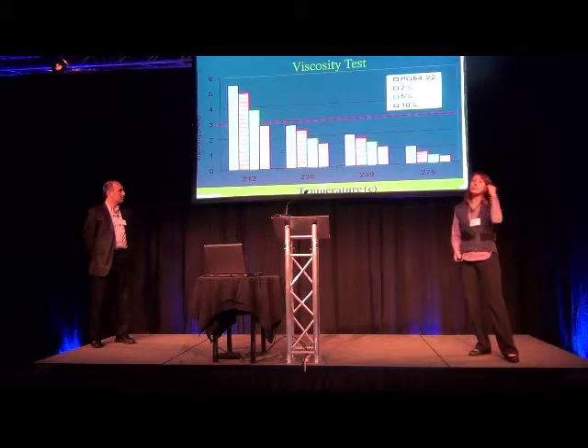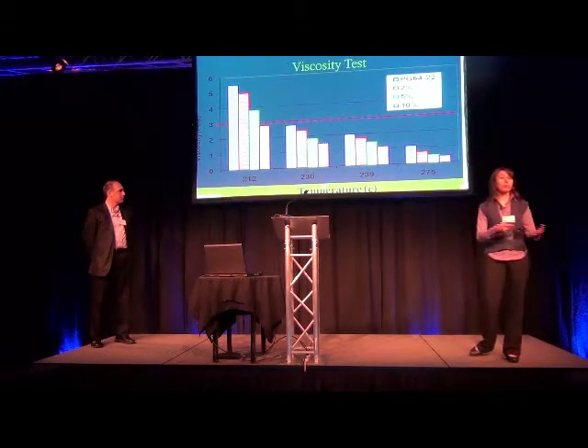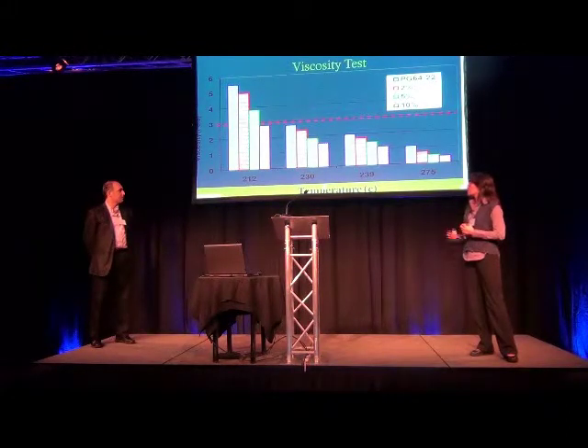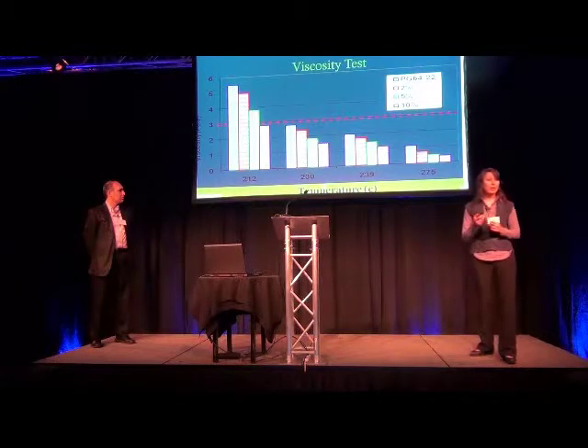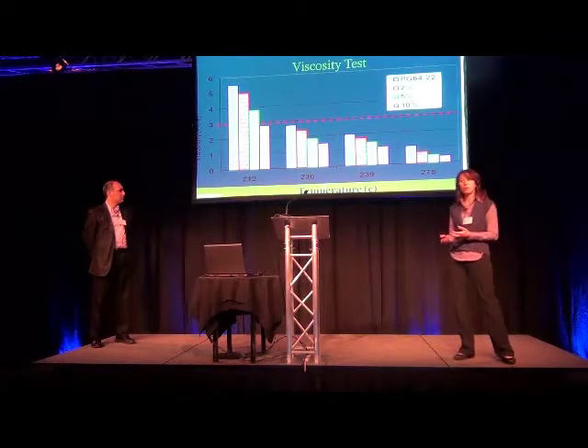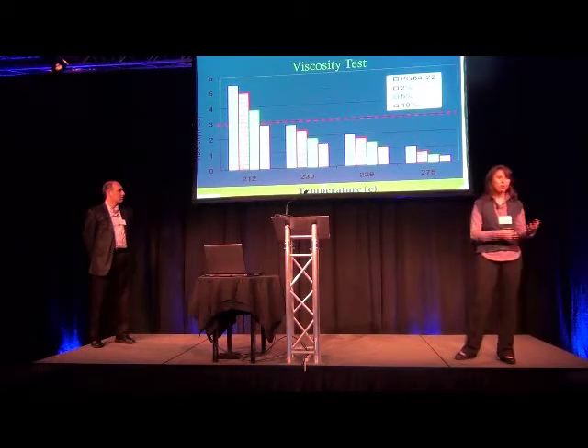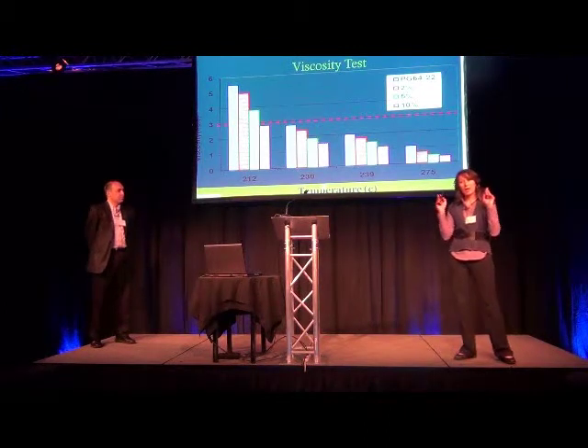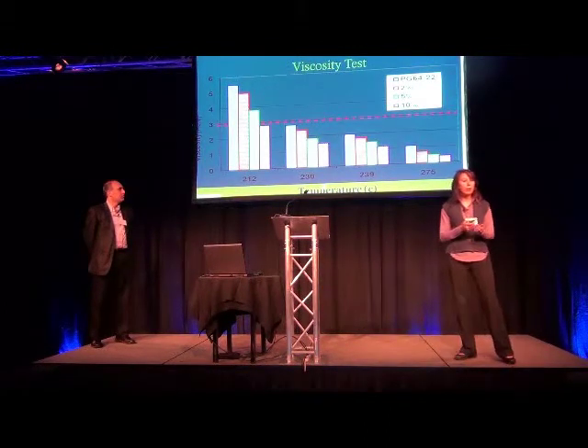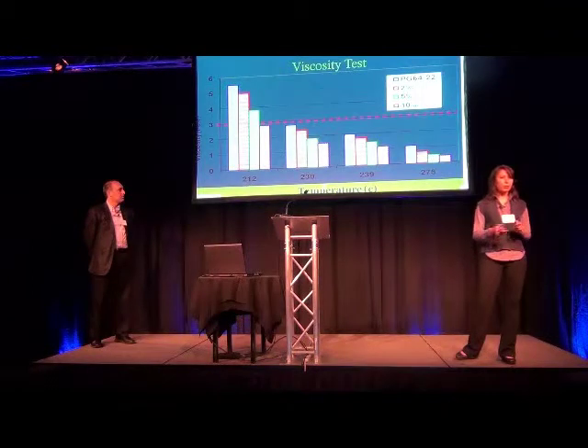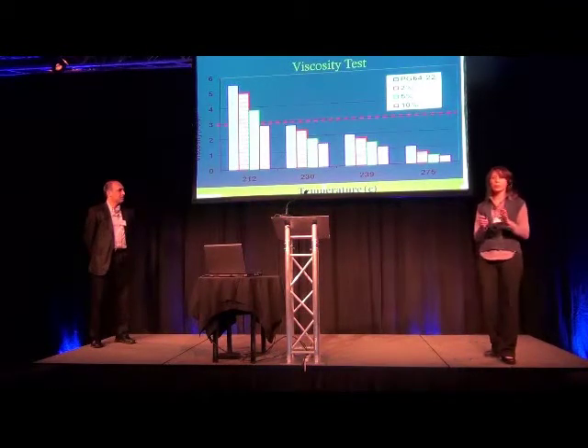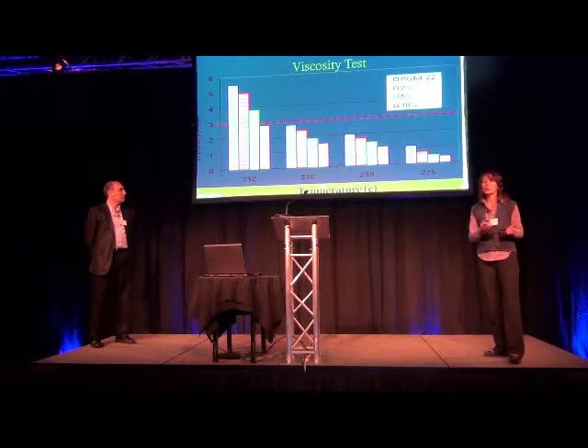So we passed the spec that DOT put forward, and we are using the Superpave specification, so we passed those specifications. But then the concern was, can we use it in the current construction, where we are using recycled shingle and recycled asphalt, and we always have asphalt present? Are they compatible? And the answer was yes. So we looked at the compatibility, phase separation, and so forth. The two materials can be used at the same time.